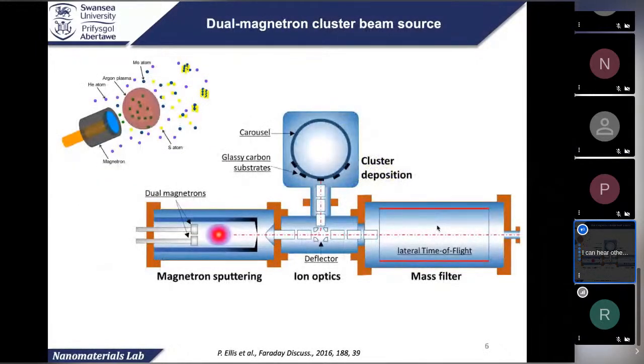Because we're trying to dope the MoS2 material, we need another magnetron. So we use this dual magnetron sputtering technique. Basically, you have MoS2 mounted in one head, and you have another material like nickel, cobalt, or iron. We tried nickel and cobalt in this reaction, but here I'll just show you the nickel. You sputter those two materials together, and if you control the power on each target, you can control the amount of, say, nickel in the MoS2.